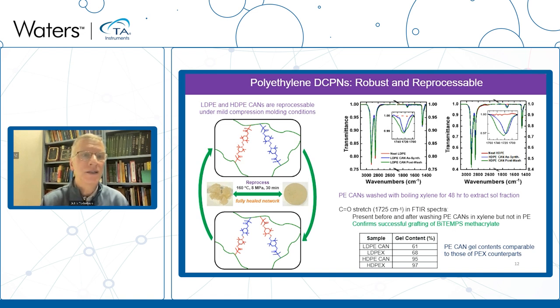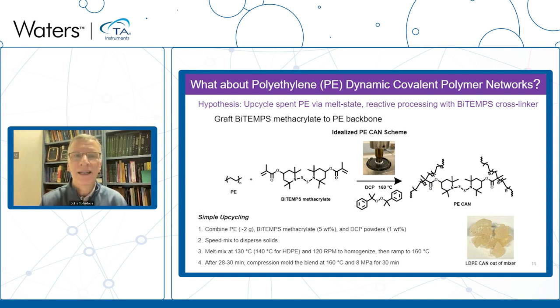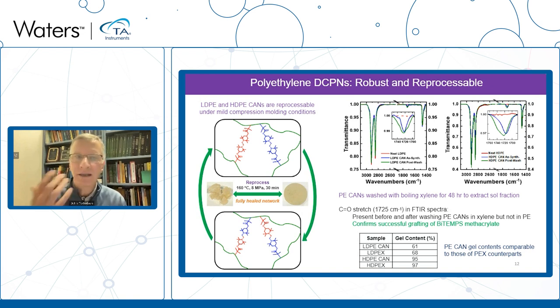So we take advantage, actually, of the dialkyl amino disulfide bonds that we had used in the previous case, the BiTEMPS methacrylate molecule, and we can take low-density polyethylene or high-density polyethylene, add 1 weight percent of a radical initiator in that system with 5 weight percent of the BiTEMPS methacrylate, and actually in this particular case, then do reactive processing under these particular circumstances and obtain a cross-linked network in this particular case. Very simple reaction, and here you see what we obtain in terms of the material coming out of the mixer. We can take that material and reprocess it at 160 degrees C and press it into a nice film. You can cut it into bits and reprocess it a number of times in these particular circumstances.